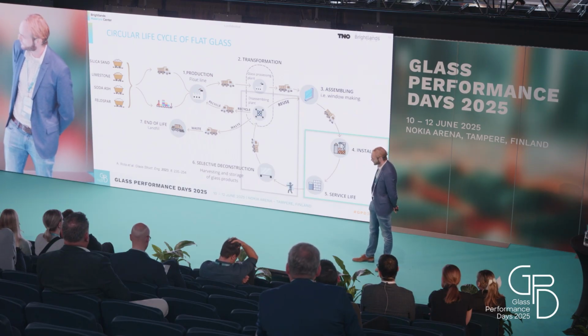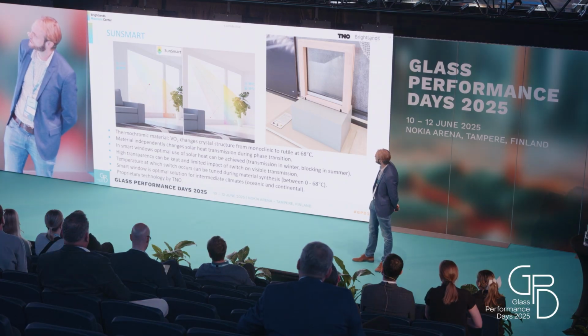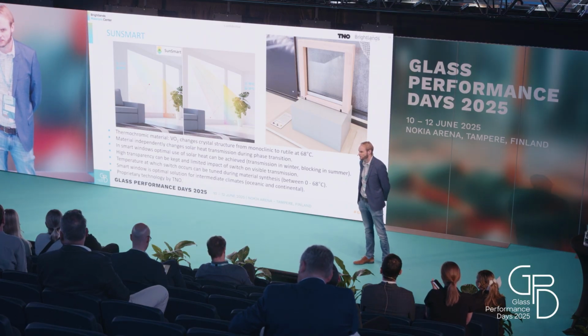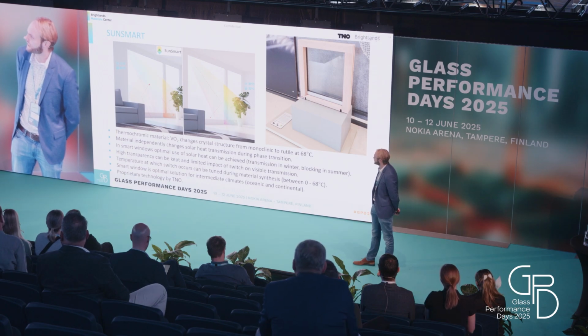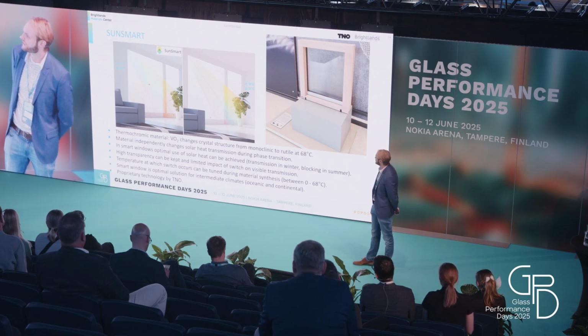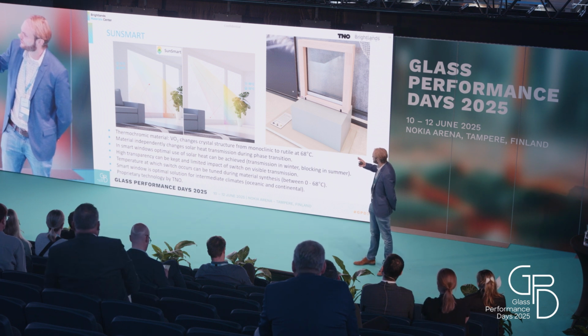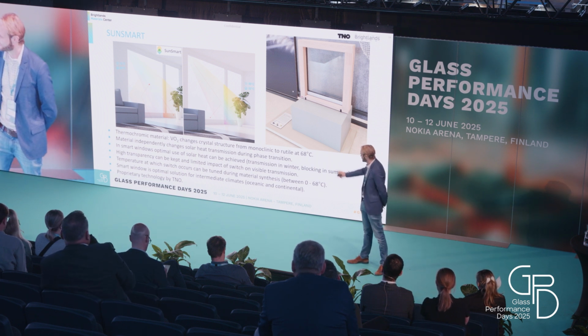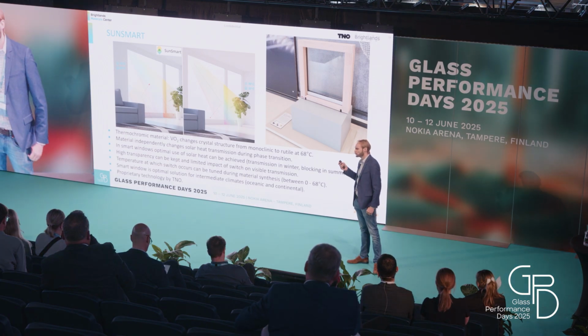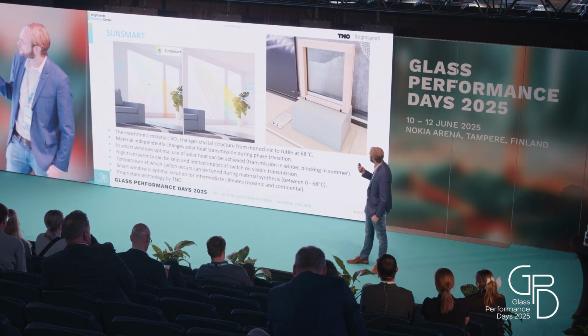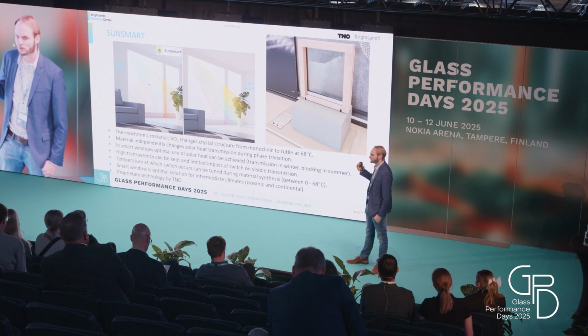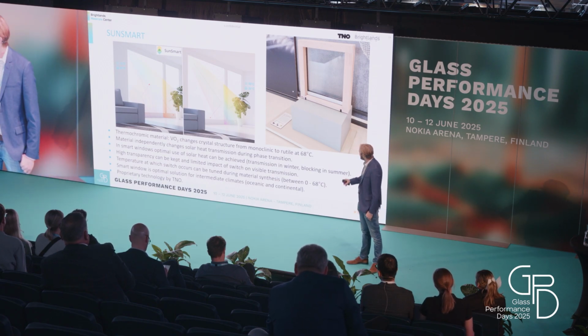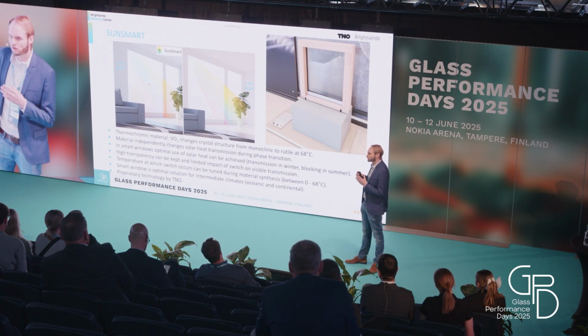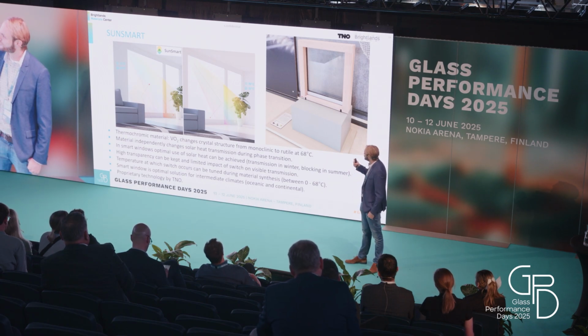So now I come to the second aspect, which is the service life of the window. And here, what we have developed in the last years is a smart window technology to optimize the energy efficiency of windows in intermediate climates. The technology that we have developed is a thermochromic material based on vanadium dioxide that can change its crystal structure at a specific temperature. And with that change in crystal structure, it also changes the optical properties of the coating and therefore the G value of the window. So the technology we have developed is completely transparent and visible, and also does not tint when it changes the properties from the cold to the hot state.